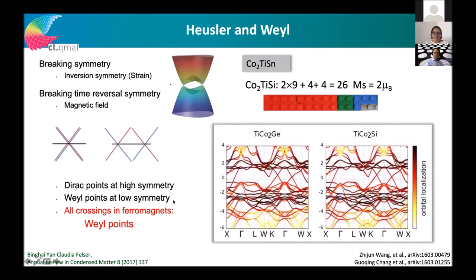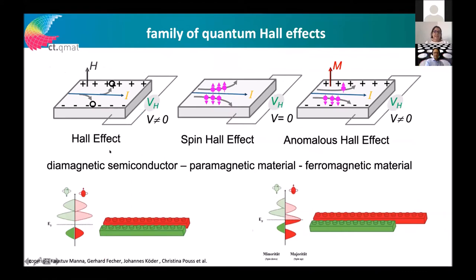Looking for simple band crossings in band structures — everybody knows spaghetti band structures with crossings — it was recognized shortly after Weyl semimetals were discussed that in a full relativistic calculation of Co₂TiGe with 26 valence electrons there are crossing points around the Fermi energy. This was the first prediction. Unfortunately, the crossing points are slightly above the Fermi energy, so this was not the ideal material for investigating these crossing points, and excitement faded somewhat.